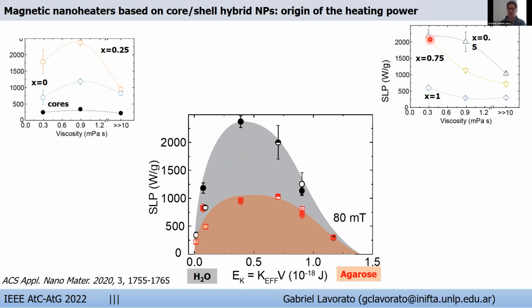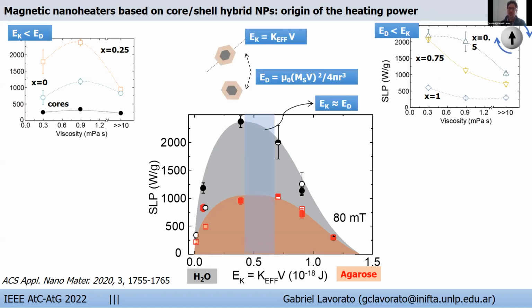Samples with large viscosity, with large anisotropy energy, show heating powers that decrease when increasing the viscosity, while samples with low anisotropies show a non-monotonic trend when varying the viscosity. Then we can draw a few ideas from these results. The highlighted part of the diagram corresponds to the region where the anisotropy energy is similar to the magnetostatic interaction energy between the nanoparticles, and so the results can be understood in terms of the ratio between these 2 energies. Then the non-monotonic trend observed for the heating power would be ascribed to a collective behavior promoted by interparticle interactions in this case.